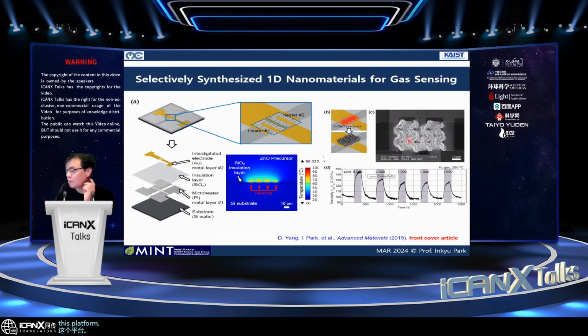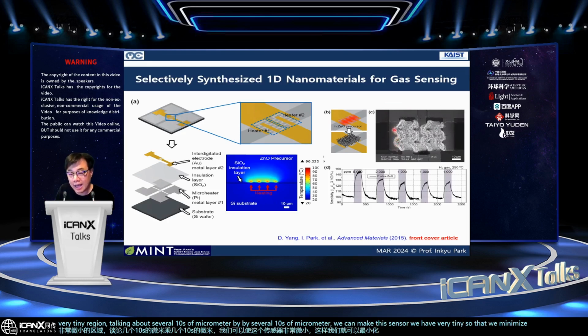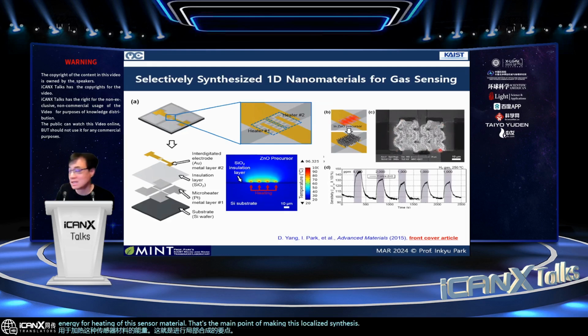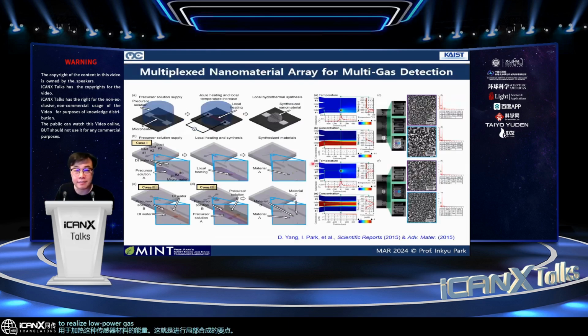And I want to point out that by minimizing this gas sensor area in a very tiny region, we're talking about several tens of micrometer by several tens of micrometer, we can make this sensor area very tiny so that we minimize the energy for heating of this sensor material. That's the main point of making this localized synthesis: to realize low power gas sensors.